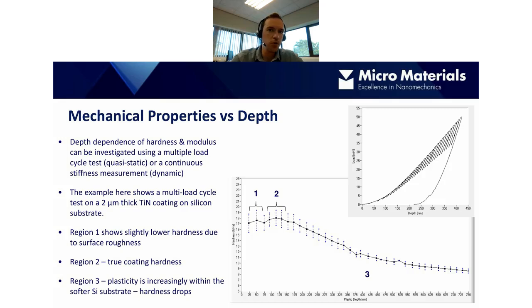So we can see these three regions here. The first region is where the hardness is actually slightly lower. This can be due to surface roughness. It can also be due to a non-fully developed plastic zone if the indent depth is very, very small. And then we see it increase and plateau. So we generally regard this plateaued region, number 2, as the true coating hardness in this case. And then, of course, region 3 is the area of increasing substrate influence.